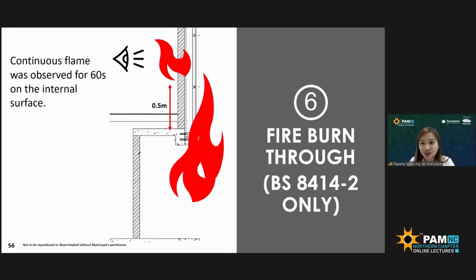And lastly, the criteria of fire burn through. This is only relevant to the external cladding that is locked onto the mild steel structures, which also means that it is only applicable to BS 8414-2. It's not applicable to Part 1, which is installed on the masonry wall. The failure will occur if there is continuous flaming at the internal surface, meaning that we are able to see the fire has actually burned through the external cladding system. If this flaming is visible and maintained for more than 60 seconds, at above 0.5 meter height above the combustion chamber, then it will be considered a fail for this criteria.